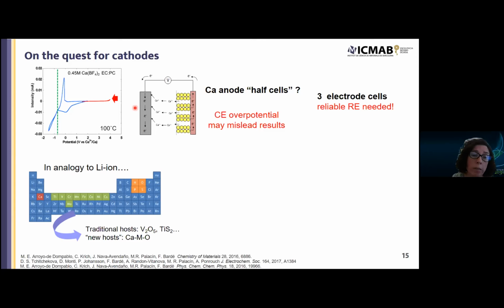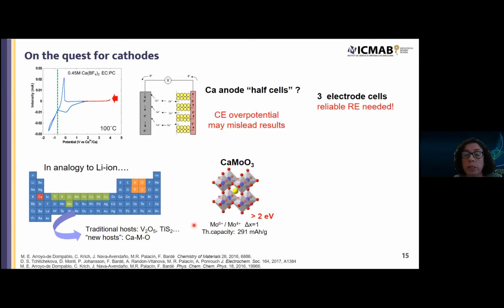And we were exploring a little bit the periodic table. We were focusing on intercalation compounds with transition metals as redox center, either having or not calcium in the crystal structure, because of course, if we have a calcium metal anode, there will be excess of calcium in the cell. And also we were exploring oxides, sulfides, nitrides, etc. And amongst these, we explored traditional intercalation hosts like V2O5 or TiS2, but also, I would say, new or potentially new hosts, which were calcium transition metal oxides.